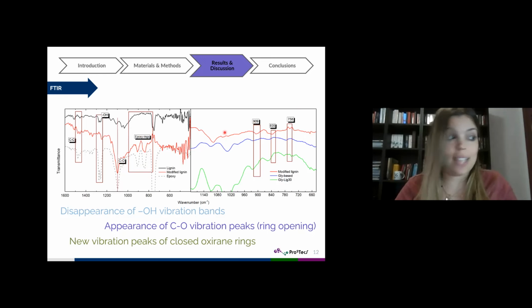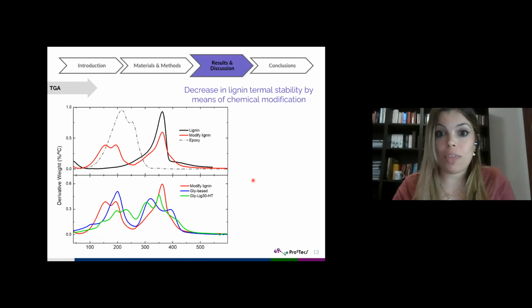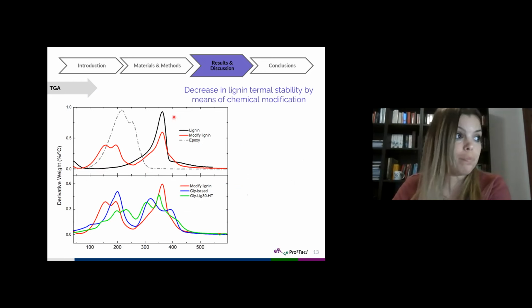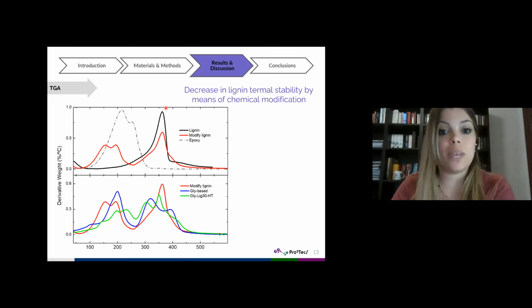In the same way, we can verify this chemical reaction by means of thermogravimetric analysis, which allows us to verify the chemical modification of lignin, as well as the interaction with NADES in the NADES formulation. For lignin, there is just one peak at around 360 Celsius degrees, which is related to the cleavage of multiple linkages forming the lignin skeleton, together with an overlapping thermal event at around 260 Celsius degrees, typical of the soft dehydration of hydroxyl groups.